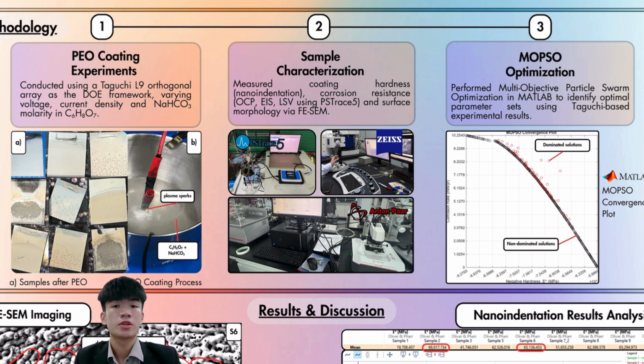Secondly, hardness testing was done via the nano-indentation method instead of micro-hardness, as micro-hardness testing is unsuitable for the thin nanoporous coatings produced via PEO in this study, as it typically requires thicker surfaces, so micro-hardness testers in this case may penetrate beyond the coating into the substrate, leading to inaccurate measurements. So the nano-indentation tests were done with the help of the company Anton Paar, where I actually went to their site located at Shah Alam to carry out the testing. This testing measured the elastic modulus of each coating to give us an idea of how the coating reacts to deformation.